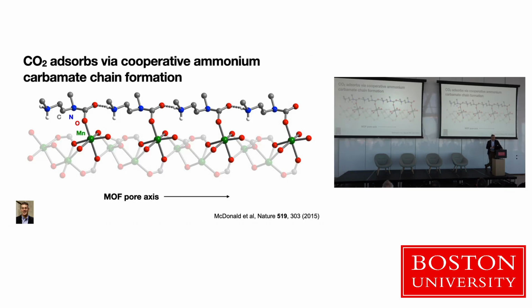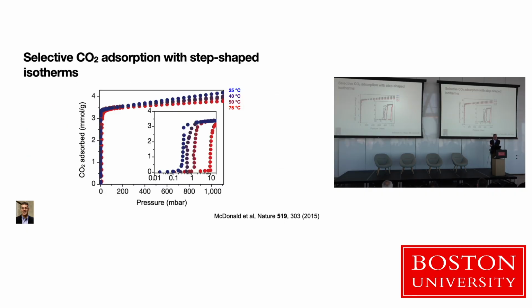this carbamate formation. And so it turns out that this is verified by X-ray diffraction and calculations, but CO2 displaces the amine, and then there's a proton transfer, and that enables the next CO2 to more readily displace the next amine. And so there's a cooperativity going on here that leads to a finite chain along the pore axis of bonded CO2 and carbamate. And the consequence of that is that the absorption profile is non-Langmuir, and so it's a step function.